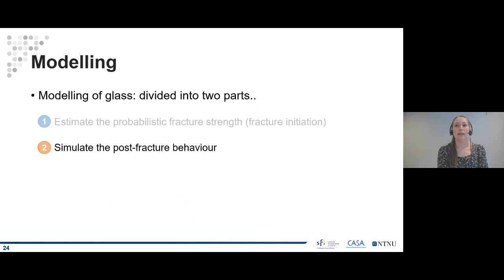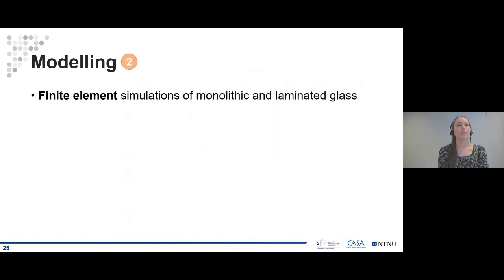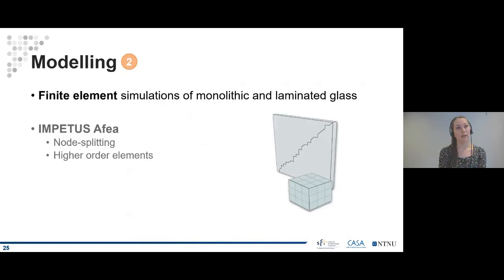Then I will go quickly through the second part of the modeling, simulations of the post-fracture behavior. Here we have used finite element simulations, and we have used several different solvers, but for this part, I will focus on simulations where we use the finite element code Impetus. This solver has some special features, including node splitting and higher order elements. Node splitting is an alternative to element erosion and can describe fracture and crack propagation by separating elements instead of deleting them. And higher order elements can provide extra robustness.